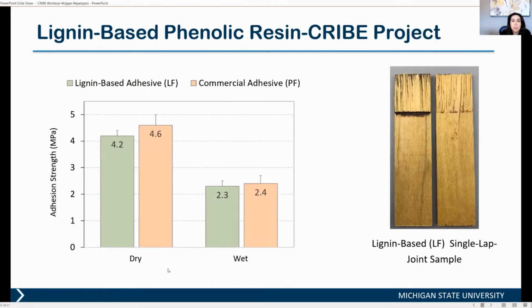This is the result that we got. We were able, for the first time, to replace 100% of the petroleum-based phenol with kraft softwood lignin, a commercially available lignin. You can see in the bar chart, the green one shows the lignin-based adhesives, and the orange bars are showing commercial adhesives. The lignin-formaldehyde (LF) adhesives generated in these projects have very good dry and wet adhesion strength, similar to the commercial adhesives. In all the tests that we've done, we basically have 100% wood failure, showing that the adhesives perform really well.